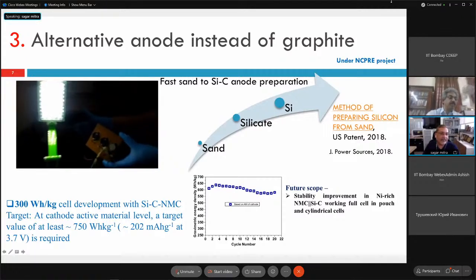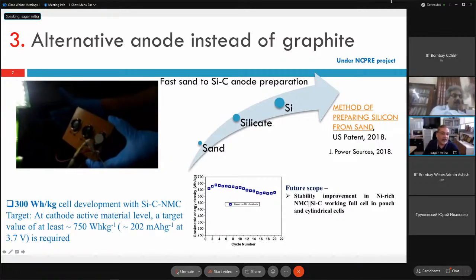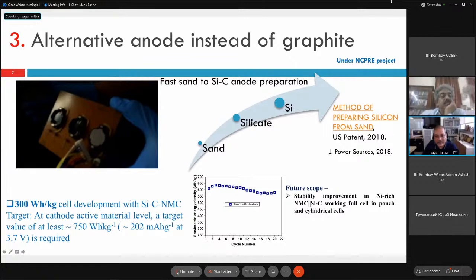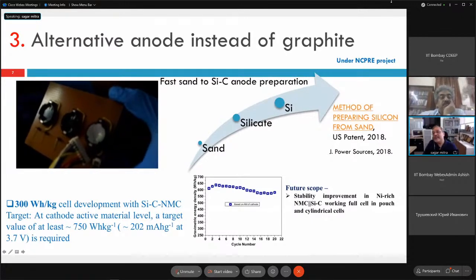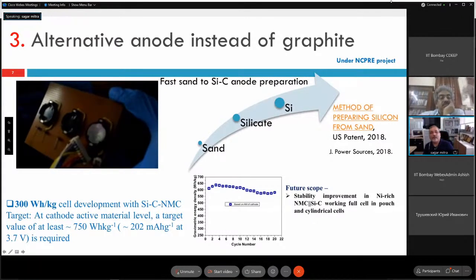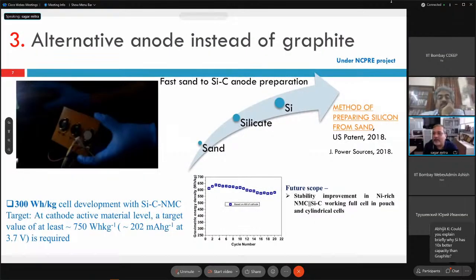To do that, our calculation says that if you have a capacity of about 750 milliamp hour per gram on the silicon side, we may achieve it. So we have almost achieved 280 watt hour per kg. And once we achieve around 300, we'll be going for a pouch cell, or large scale making of cells. So that's our target.